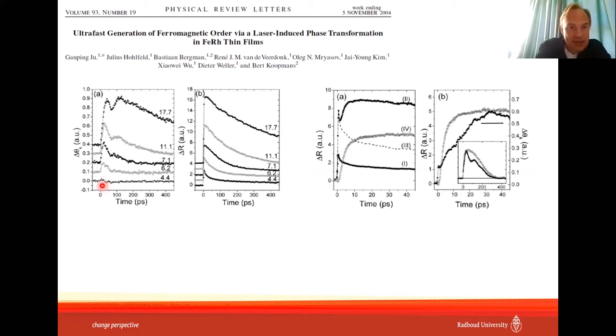So here I show the dynamics of the magneto-optical Kerr effect for different fluences from 4 millijoule per square centimeter to 17. You can see that with increasing fluence of the excitation, at low fluence practically nothing happens. Then we see an increase of the magneto-optical Kerr effect, which was interpreted as an increase of the magnetization. And something interesting also happens in reflectivity. They analyzed how the reflectivity changes, and they saw that the reflectivity has two contributions. One is very fast, which looks very much like a contribution from hot electrons. The electrons first become hot in the material, and then they partly cool down due to spin electron lattice interaction.